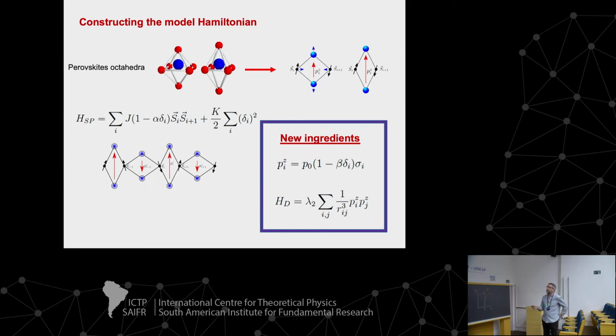And for the magnetic system, this was inspired by previous papers talking about a magnetostriction scenario. So this is the so-called and well-known spin-Peierls Hamiltonian. You have the spin variables interacting via exchange, these black arrows here. The ingredient that makes it a spin-Peierls system is that the coupling between neighboring spins can vary depending on the distance between them. This is a kind of trivial modelization. And then you have the elastic energy here.